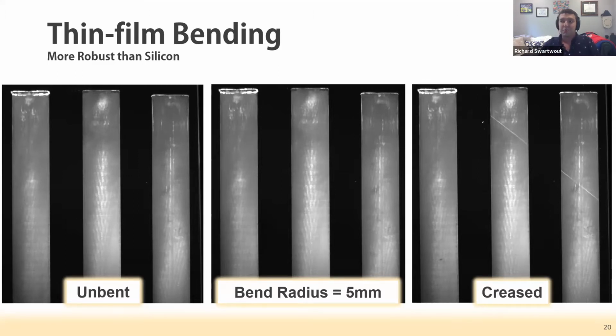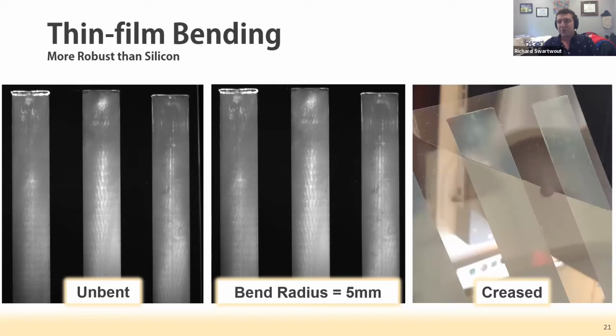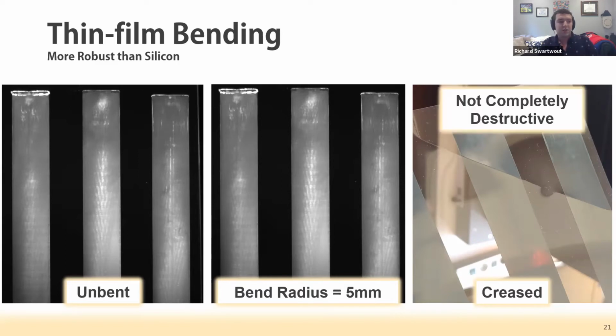Here it's actually a PL brightening. Under a real image, there's no cracking, there's no delamination. It's mostly just substrate damage, and so most likely this is not completely destructive damage. Therefore thin films are actually just fundamentally better at being in flexible form factors than silicon-based technologies.